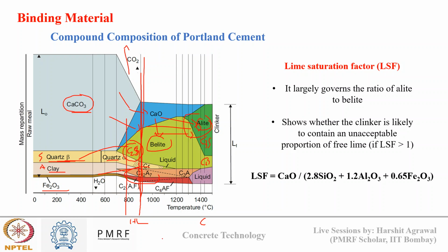Now once the clinker is produced after this heating phase, there is one initial preliminary quality assessment of clinker that is done, known as the lime saturation factor. So what is this lime saturation factor? It governs the ratio between alite and belite, the C3S to C2S ratio. What this ratio tells is whether the clinker is likely to contain an unacceptable proportion of free lime or not.